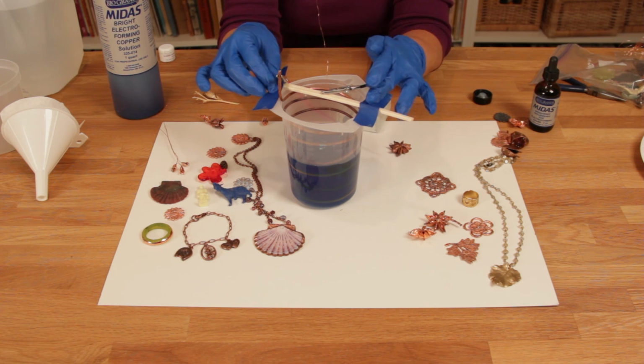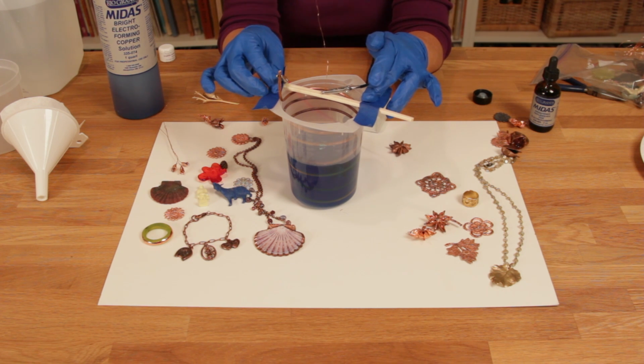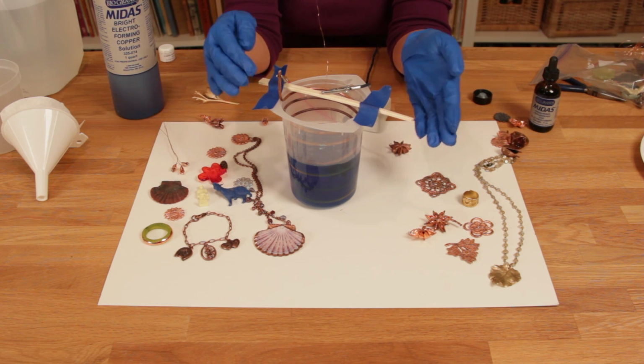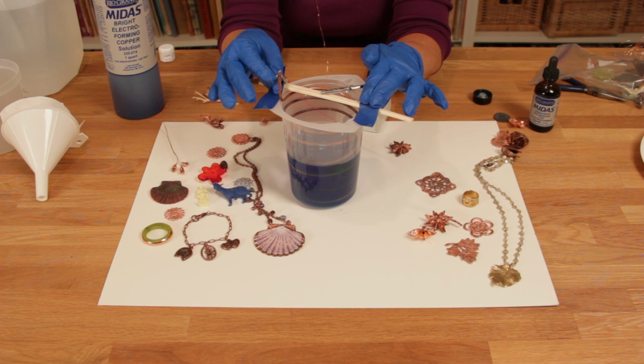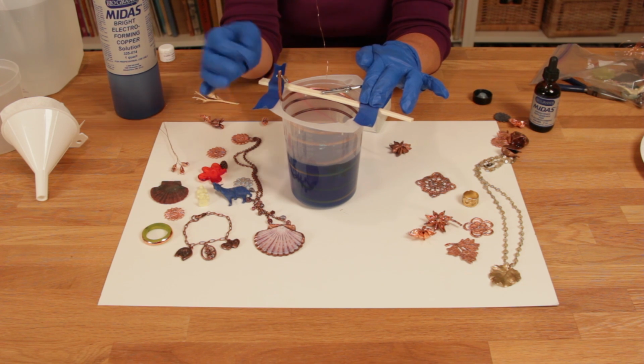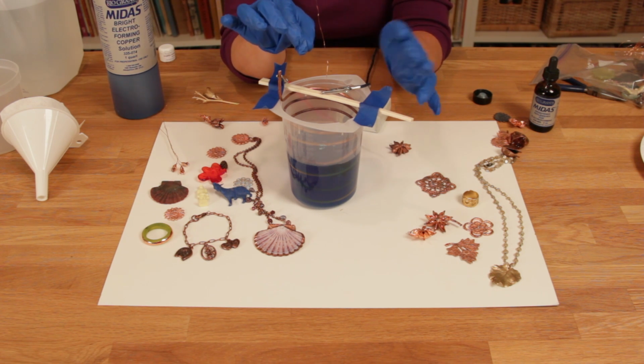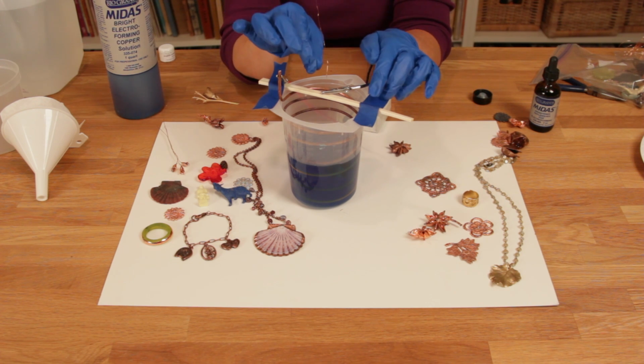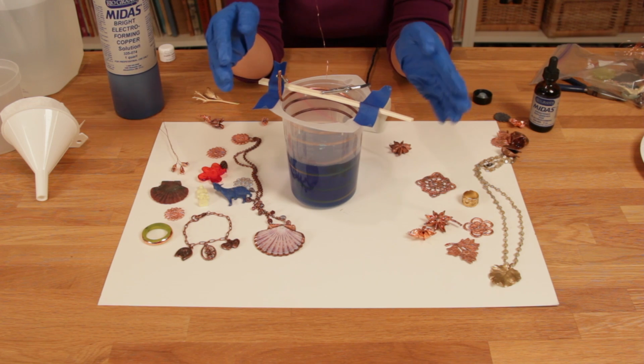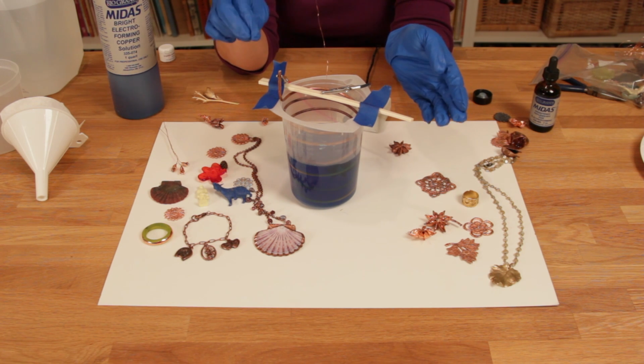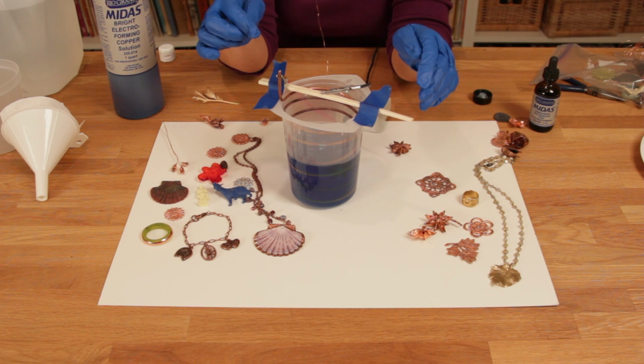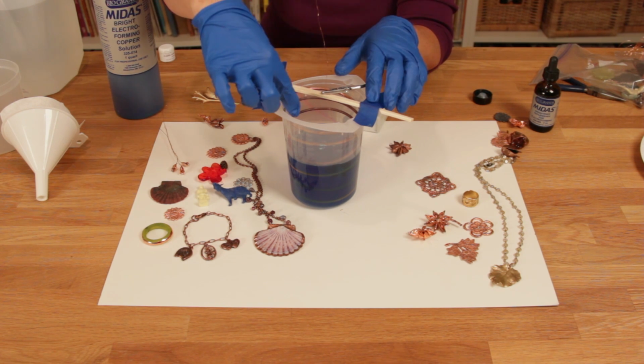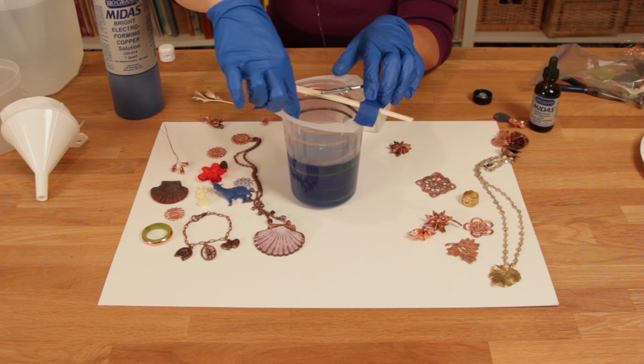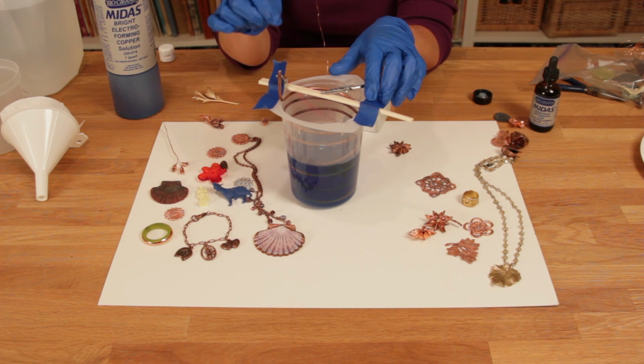The first one is the process works much better if you have a warm room. If you have the temperature between 75 and 80 with a little heating pad or something warm around the beaker, that will help immensely. You can also use agitation in the form of a small fish tank bubbler with a hose attached, and just place the hose without a stone or anything else, just the plastic hose, inside the solution, and that will create a little bit of agitation that will keep the copper particles moving. And what's happening during electroforming is the copper is moving from the coil onto your piece. So you will see this coil diminish the more and more you electroform.